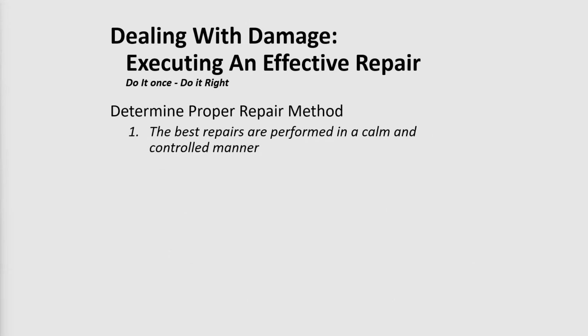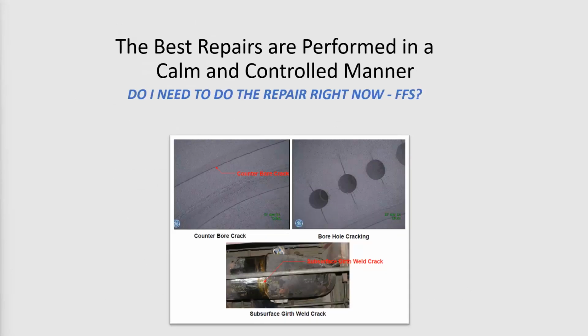A couple of other considerations: it's always best to carry out repairs in a controlled manner. If you can avoid doing the repair immediately, if you don't have a good understanding of exactly what the root cause of the damage is, and if by doing a fitness for service study you can demonstrate that you can operate with some level of damage in a component, then in those cases the most appropriate thing to do is to defer the repair until there's a better understanding of what the cause of the damage is, and then when the appropriate time comes, carry out the repair in the most effective manner.